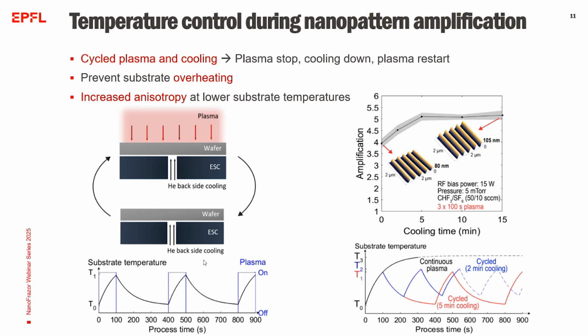Beyond these parameters, we have also implemented a cycle dry etching process. This cycle process alternates between plasma etching and cooling cycles to prevent the substrate from overheating. And precise temperature control is really crucial for maintaining the sidewall protection on any grayscale or binary shapes, which allow for higher anisotropic amplifications. So only vertically amplify and the sidewalls are protected at relatively lower temperatures.